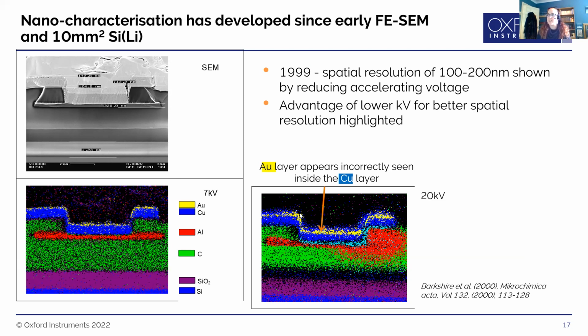You've got a lot of blending here. The gold layer here looks like it's inside the copper. And you've got the aluminium layer kind of spilling out into the carbon. Whereas if you drop that voltage, you can get much better resolution. And this is quite a long time ago. This is with some liquid nitrogen cooled detectors, I believe.